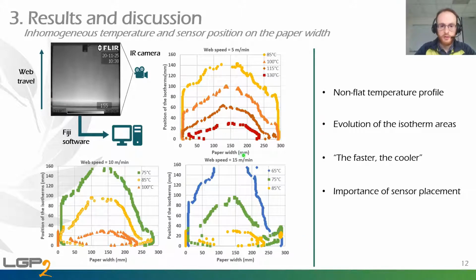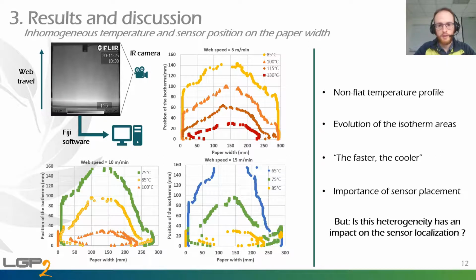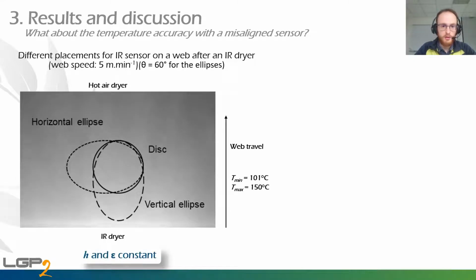In fact, when the speed increases, the maximum temperatures of the web decrease. And it also seems that there is an importance of sensor placement on the web width. In fact, if you put the sensors here or here, you will not have the same information concerning temperatures. But now, do these variations of temperatures impact the readings? In fact, it seems to be yes. When we have different placements for infrared sensors on the web after an infrared dryer and put two ellipses, one horizontal and one vertical, and a disk, we don't obtain the same values.